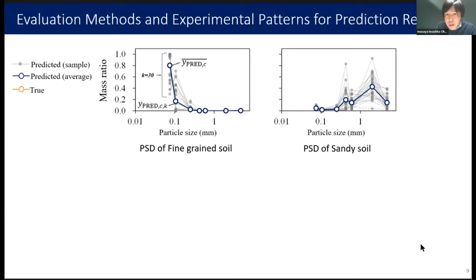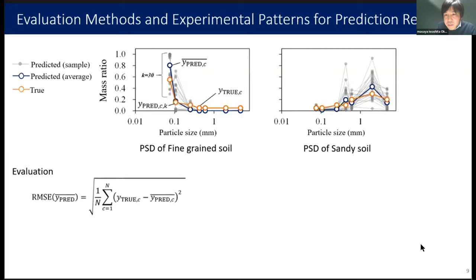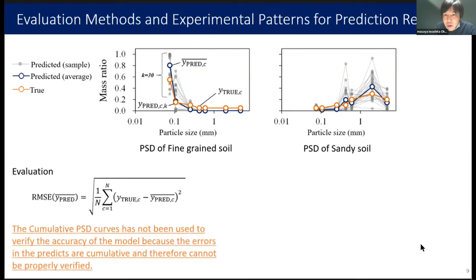The predicted results obtained by averaging are compared for accuracy by taking the root mean square error with the true value of the particle size distribution. Note that although a cumulative PSD curve is often used to confirm the particle size distribution, that curve is not used in this verification. This is because the cumulative PSD curve is the result of accumulating particles in order of fineness, and prediction errors are also accumulated. Therefore, the accuracy of the model cannot be properly verified.